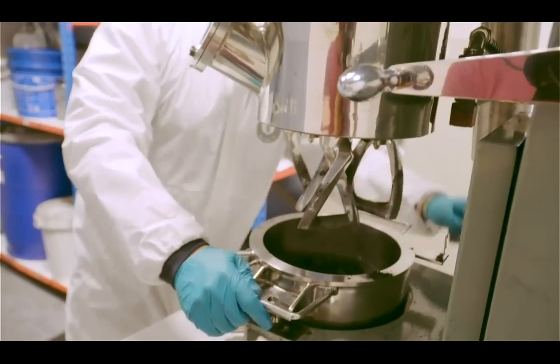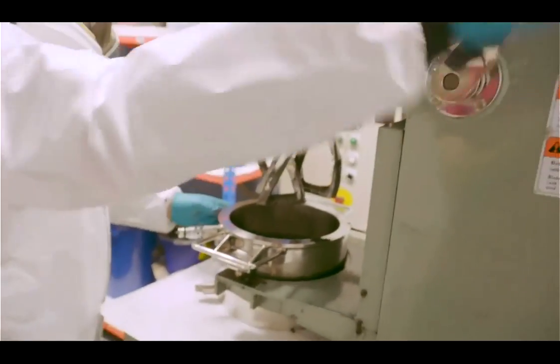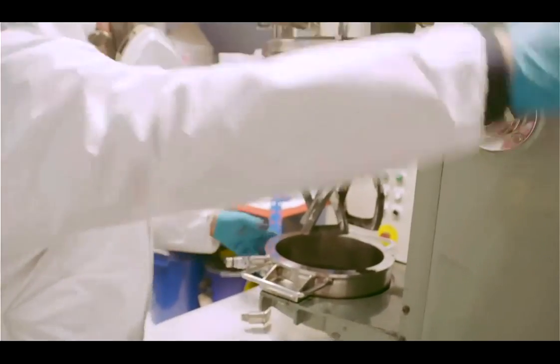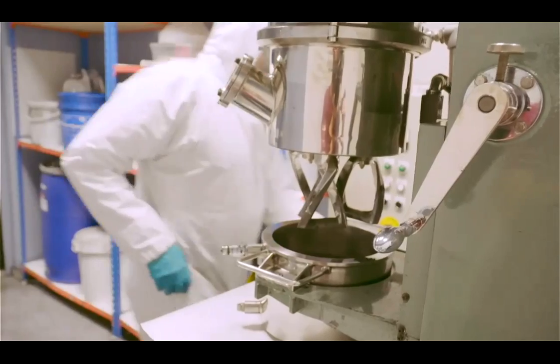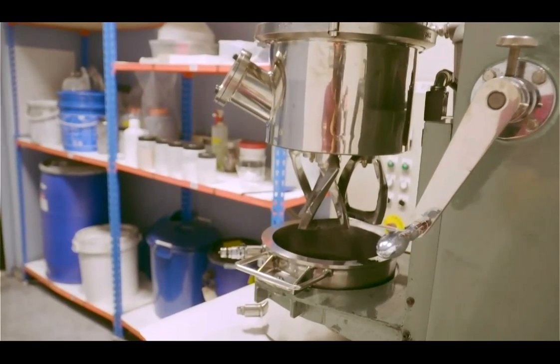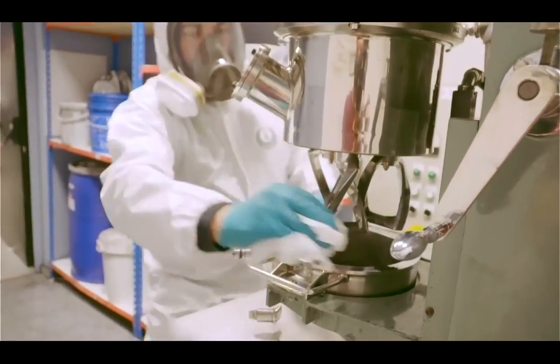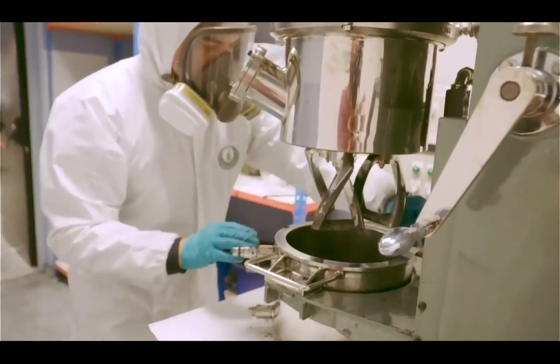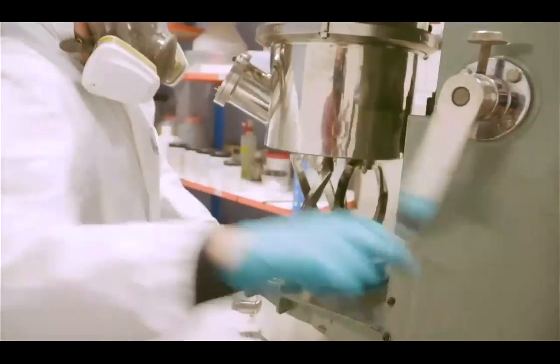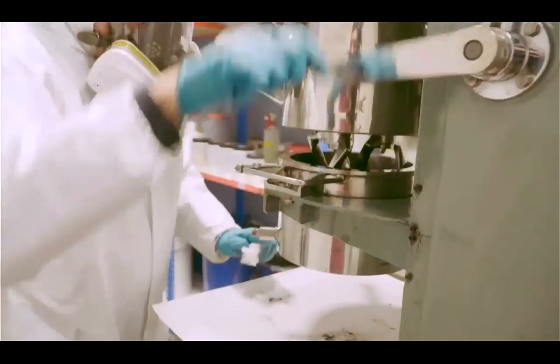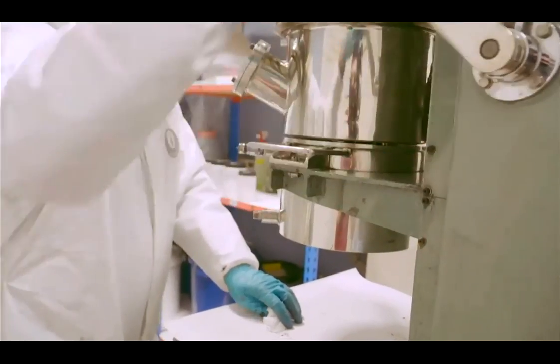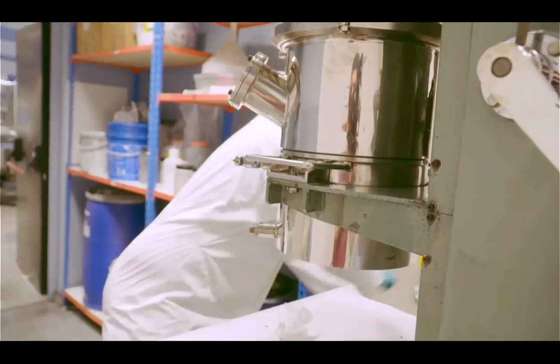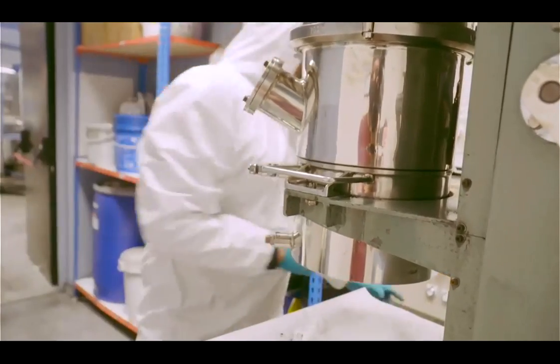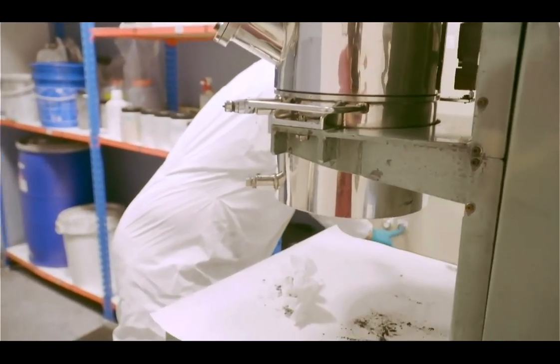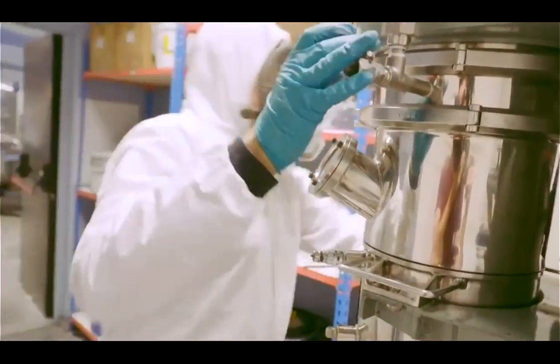So a typical anode formulation is composed of graphite as active material, approximately 90% in weight, conductive material, carbon, 5% in weight, binder, SBR, and we use CMC as a dispersant, 2% in water. In general, we try to process the anode in water. Not all active materials are, in general, very hydrophobic and very difficult to process, but having these planetary mixers will allow us to prepare the slurries in water.